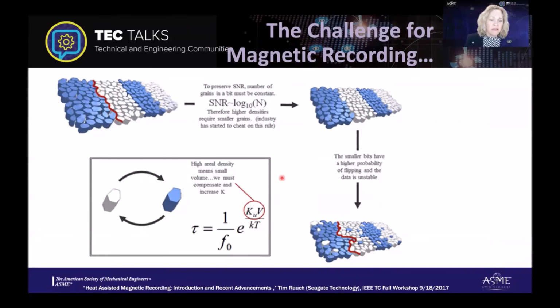The problem with this is that if we look at the energy and the time to be able to randomly cause a grain to flip its magnetization, this could just be caused by the thermal energy at room temperature. You want grains to not be flipping very often. If this is somebody's bank account or picture of their child, you want these grains to be very stable. And so this time in between events at which you have a probability of a random flip, we want it to be very, very long. And so we want this number to be big, and we want it to stay constant over time.